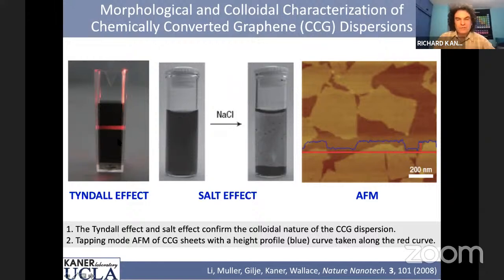And we know that because it shows the salt effect. So if you take any salt, and sodium chloride will work, it simply neutralizes the charge and they all flocculate out. And if you take these pieces and you look at them under an atomic force microscope, you can see you have very large pieces of chemically produced graphene. And here's an AFM probe, and you can see about a 1 nanometer step height. And this is one way of looking at graphene. Of course, we heard earlier that a better way is to look at Raman spectroscopy, and there's many other ways. But at the time, these were some of the largest pieces produced. And this method is quite useful, easily scalable.